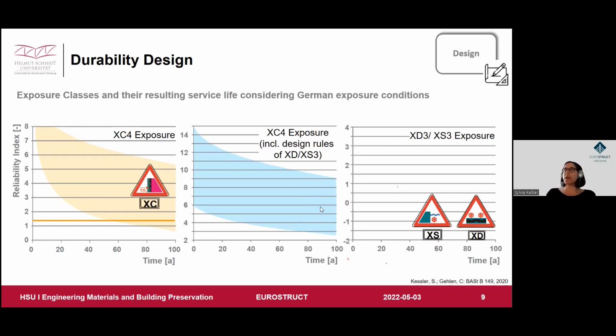And this is the range of the reliability you can get just applying the Eurocode exposure class rules in order to ensure normally a service life of about 50 years. And you see here now, this is a normal limit state, the reliability index of 1.3, which is equivalent to more or less 10% of failure probability, so 10% of corrosion probability.